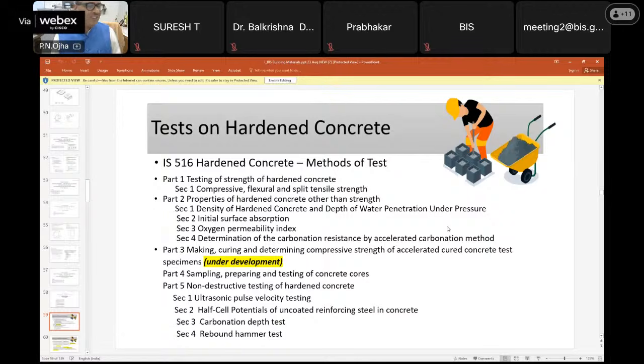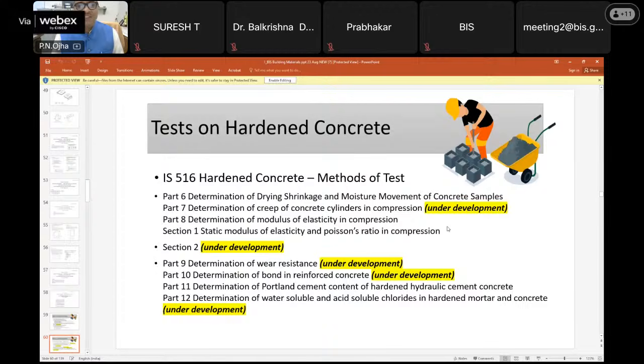And the rebound hammer test is based on the rebound from the concrete surface, and to some extent it can be related to the strength of concrete, but it should be interpreted along with the UPV and the core test. So for this rebound hammer test, how to do it, how to make a grid, and how to interpret the results. All these tests are in the IS 516 series, a standard is available. And this is a hardened concrete method of test.